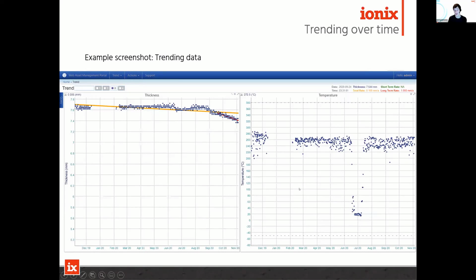You can also see in this example that the temperature of this pipe, the asset, dropped from operating at 260 to 280 degrees C down to close to room temperature ambient. And there was only a very, very small change in the measurement observed here. So there's the excellent temperature compensation.